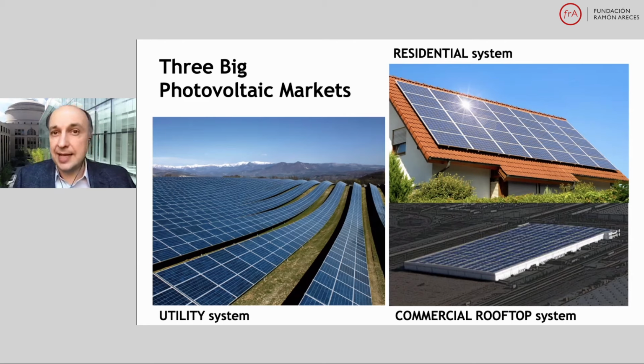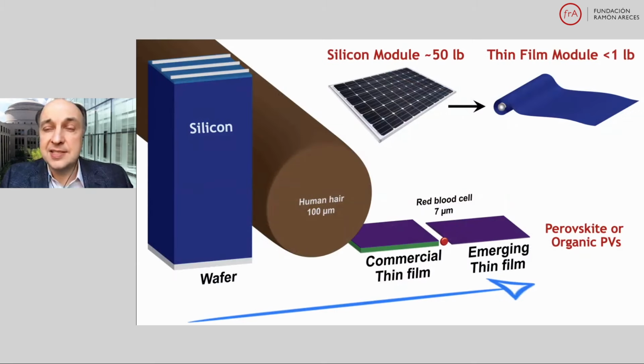Silicon is an indirect bandgap semiconductor. It doesn't absorb light as efficiently as the nanostructured materials we use. Nanostructured materials like molecules, polymers, and the latest ones called perovskites are particularly exciting as they provide high efficiency and simplicity of manufacturability. In each case, if you use a nanostructured material, you need only a micron or less of the material, compared to a silicon cell that may be a 150 micron thick wafer. Because a silicon wafer is so thick, 1.5 times the thickness of a human hair, it is also brittle. As a result, we mount it onto 3 to 4 millimeter thick pieces of glass. Hence a silicon module 1 by 2 meters in size might weigh 50 pounds, 25 kilos.